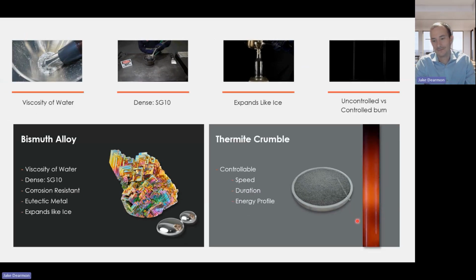If we look at the other pillar, and that's thermite, nothing's new about bismuth alloys. Some of the first patents we found going back 40 or 50 years were actually filed by the Schlumberger brothers, where they were looking at using bismuth-based alloys to seal different applications downhole using electric heaters. Electric heaters, you have to have an umbilical back to surface, or you're running E-line with high voltage. It's hard to get a lot of energy into that heater to be able to melt it. There comes the thermite, which is a chemical reaction of iron oxide and aluminum that once it's reacting generates a lot of heat, and it has an enormous heat density and energy density in it. So we're able to use that thermite to actually very quickly melt these alloys.